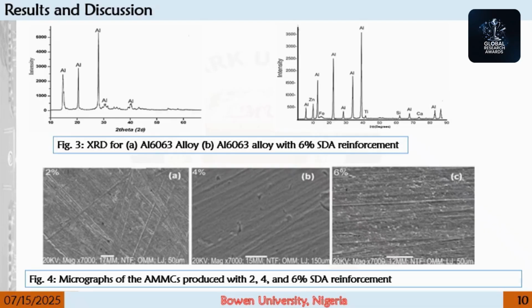It can be observed that the diffraction peaks appear in a pattern that corresponds to a phase of a good crystalline structure and support the fact that there was a proper mixing of the SDA within the matrix. The micrograph seen in Figure 4 displays uniform distribution of the SDA in the aluminum matrix showing low porosity, and this can be attributed to the stir casting route used in fabricating the composite, which allowed proper dispersion of the reinforcement.